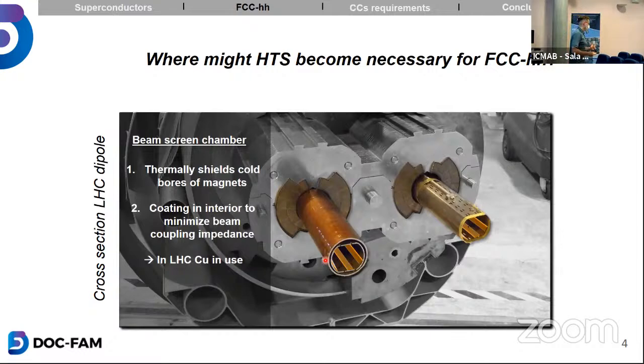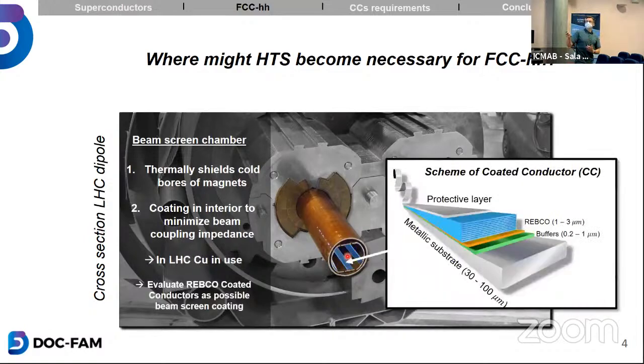However, as I mentioned, for the Future Circular Collider, the energies will be bigger. The synchrotron radiation will be bigger, and thus you have to increase the operational temperature of such a beam screen chamber, and at this temperature, the surface resistance of copper might not be low enough to guarantee a stable beam. For this reason, we propose to use coated conductors instead. It is basically the high temperature superconductor that I was talking about, YBCO, but it is on top of a flexible substrate, so it makes it more applicable for any kind of application, okay? And it's also protected. So the goal of my thesis was to evaluate if these kinds of coated conductors can be used as a good beam screen coating for the Future Circular Collider.